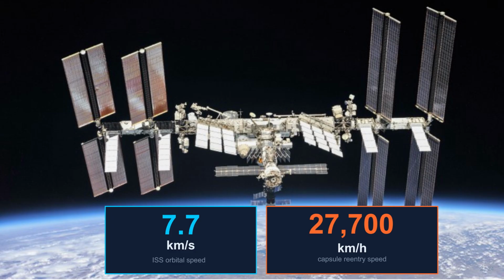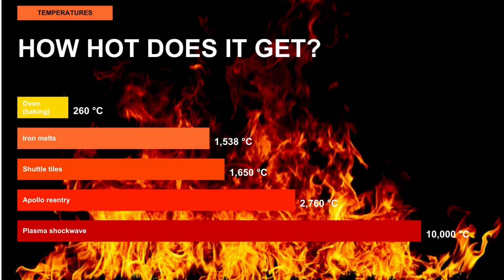Peak heating occurs between 60 and 80 kilometers altitude, where air density is just high enough to compress but still thin enough for the vehicle to be moving fast. Surface temperatures during reentry depend on vehicle shape and entry angle. Apollo capsule peak reached approximately 2,760 degrees Celsius at the heat shield face. Space Shuttle leading edges was up to 1,650 degrees Celsius. For reference, iron melts at 1,538 degrees Celsius. Aluminum melts at 660 degrees Celsius.